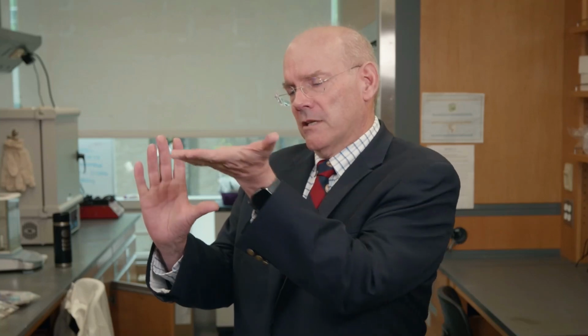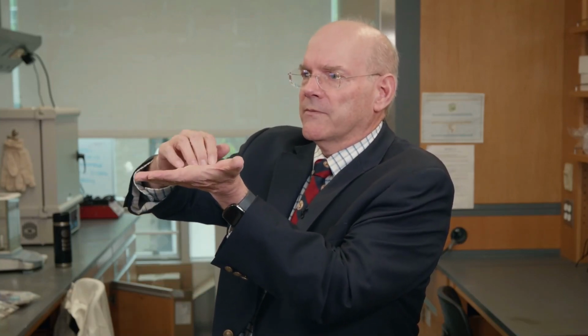Calmetrics makes X-ray fluorescence calibration standards. X-ray fluorescence is a method that lots of companies use and lots of people use to measure materials. Basically, if you have a material, you shine X-rays on it. The X-rays cause the material to fluoresce. That means it emits other X-rays, and you measure the X-rays that are fluoresced, and you can find out what elements are in the material, and you can also use it to determine how thick a layer is. So companies that make thin coatings like to use these machines to measure the coating thicknesses.